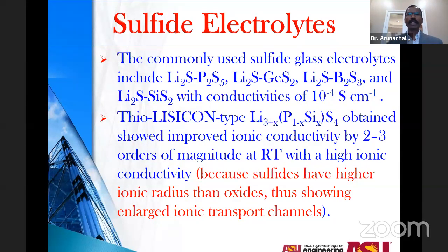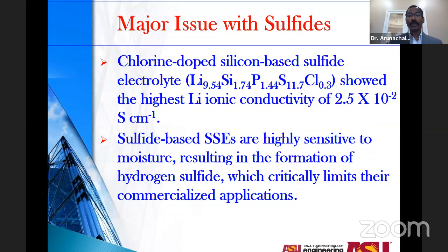Sulfides are relatively cheaper too compared to other materials, but again they have some issues. One of the materials very recently reported is the chlorine doped silicon sulfide. You can see the structure here, the formula. That material showed almost 2.5 × 10⁻² per centimeter.